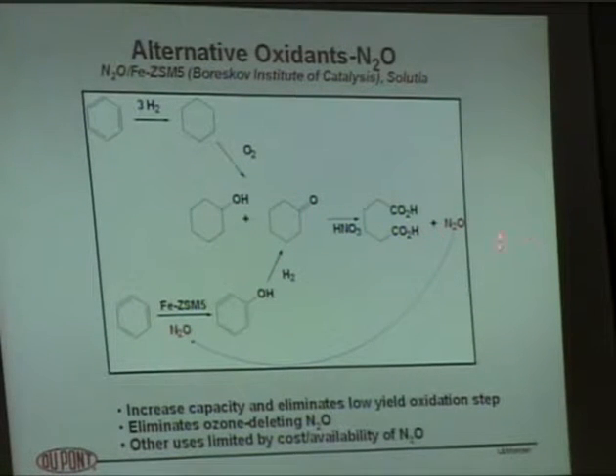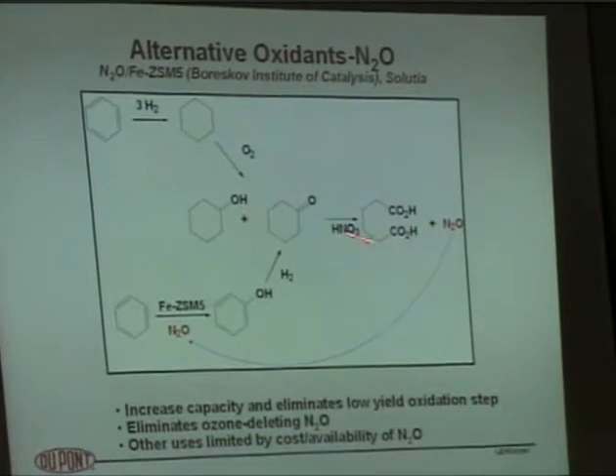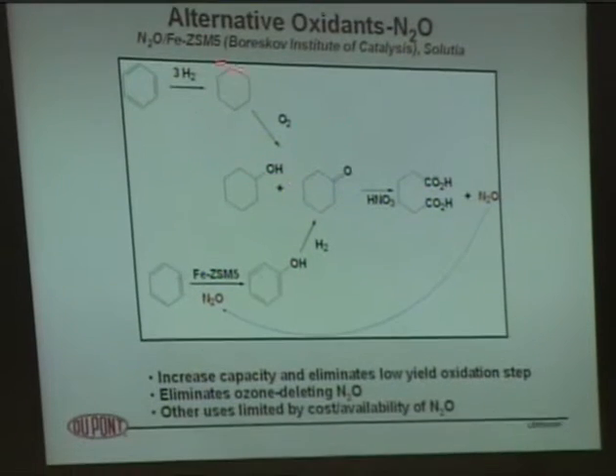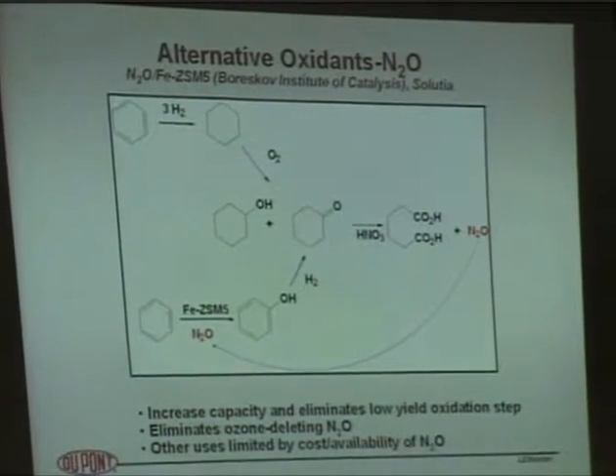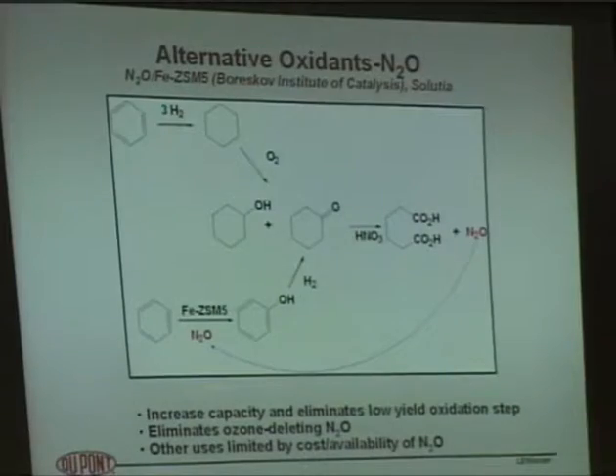So by using this N2O, you can get incremental capacity in the plant to make phenol, and then convert that into adipic acid. There are several advantages in this process. One, the biggest advantage, is that you're avoiding the least selective part of this whole process, which is the radical reaction of making the ketone and alcohol from cyclohexane, because you're coming in here now, you're making cyclohexanone in very high selectivity. So as a way to expand adipic acid capacity by using that N2O, this is economically a wonderful incremental improvement in the process.